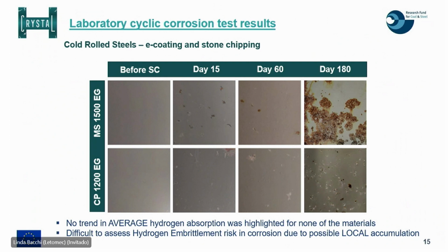What we discussed together with other partners of the project was that maybe we can have some very local hydrogen accumulation, and so all of the testing methodology that we can apply are considering an average measurement of a certain area or of a certain part of the sample, and so we were not able to assess the hydrogen embrittlement risk during this corrosion testing.